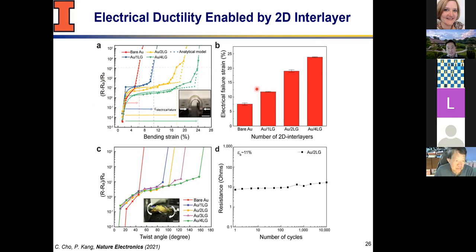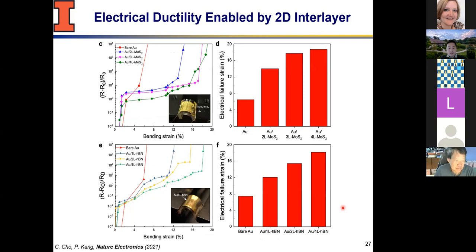And this behavior isn't just for bending, you can do twist. That really shows how robust this is to large twist angles by having additional layers of these material added in there. So really, it seems like this is happening, and it's consistent across, and it's enhanced even with more layers of graphene added. And here is also the fatigue response, or the characterizations, where the cycle performance really isn't perturbing the failure of this material, this system.